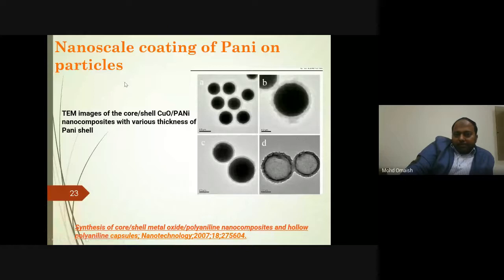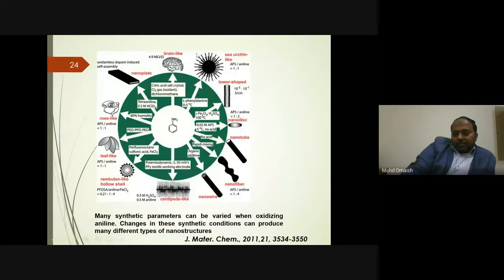In this paper, the authors have coated polyaniline on copper oxide. So polyaniline can also be used for coating on nanoparticles and nanosheets, and we can easily get a very good, uniform and thin coating by managing the reaction conditions. But if you use a large amount of monomer, then you'll get bulk polymers.